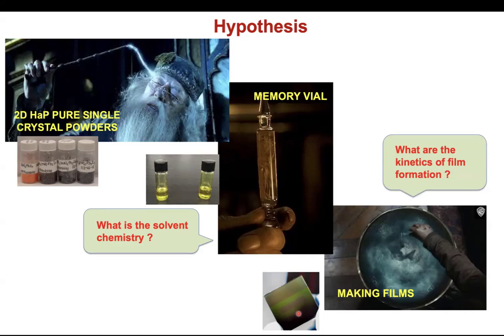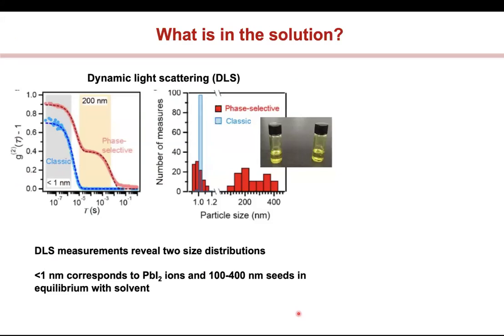So we set out to understand that. And the first experiment that we did was something called dynamic light scattering. Basically, what you're looking at is a light beam that is going through your solvents, which are like this. One of them is this classical one, which has all these precursors mixed. And the second one is where we take these crystals and we dissolve them into the solvent. They both look identical, but when we look at the dynamic light scattering, they give you very different results.